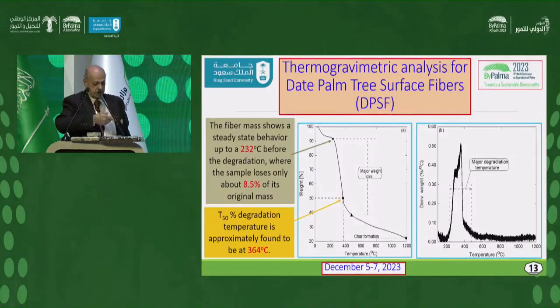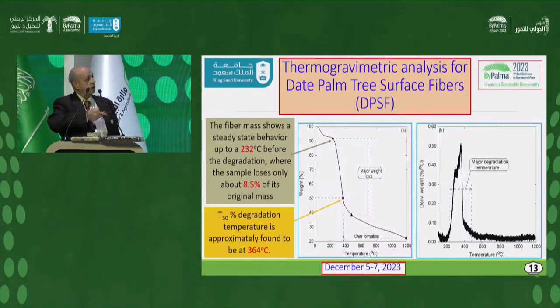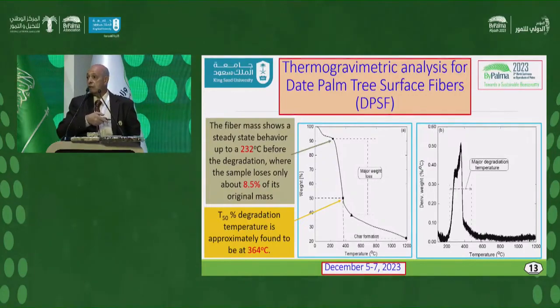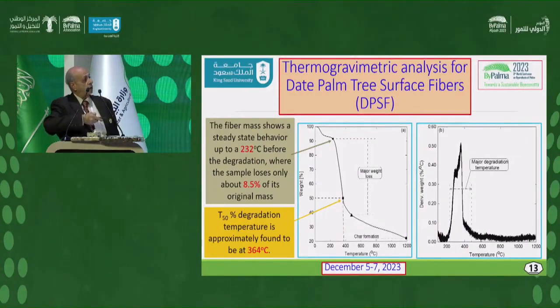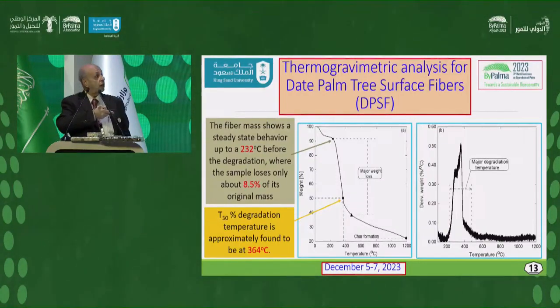This is the TGA for that, which shows that the palm tree surface fiber is stable up to about 232, where it only loses 8.5%, which could be related to the water vapor vaporized in that range. And this is the degradation temperature, with 50% degradation at about 364. So if you compare this, it's very good to be used as an insulation since it is stable up to this temperature. And this is the derivative, which shows that the major degradation occurs in these two temperature limits.